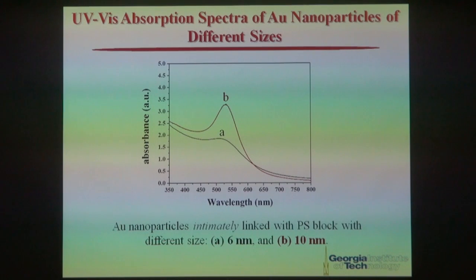So now, here's a question you might want to ask. So the particles you prepared by this copolymer nanoreactor approach have as good physical properties as the particles made by other means or not? So this is the question I want to address in the following 2 slides. Give you 2 examples. So the first one is the gold nanoparticles capped by polystyrene. So here you see the plasmonic absorption from gold nanoparticles corresponding to the particle size of 6 and 10 nanometers respectively. With the increase in particle size, we see the increase in plasmonic absorption. So this one actually is consistent with the report in literature.